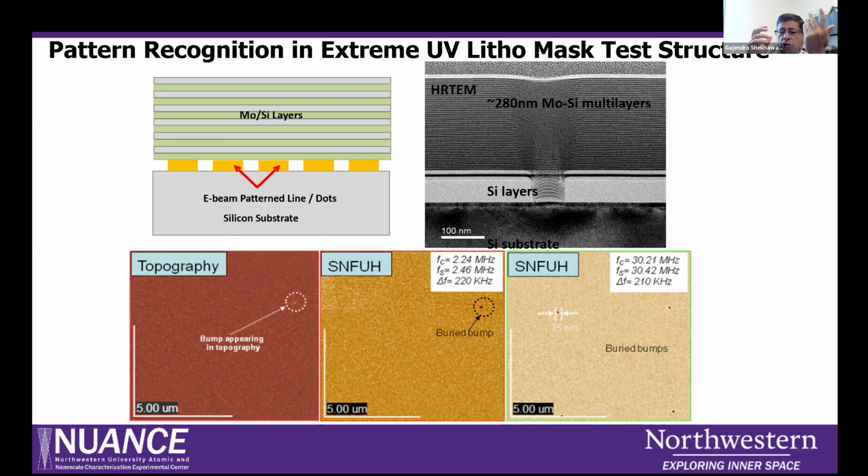But these defects are created defects, because they want to see that if we create a defect at such a depth, can we see it? And then when we increase the ultrasonic frequency, what happens? The penetration depth decreases. Okay. You lose signal intensity, but there are ways you can increase the signal intensity.